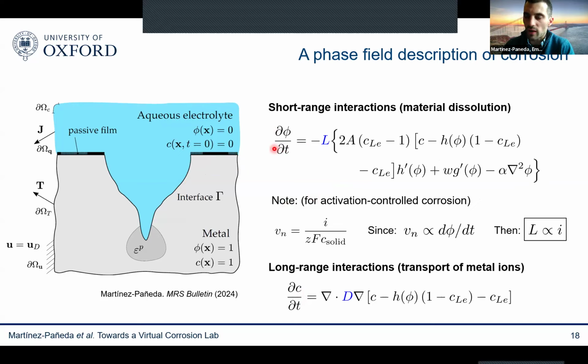An equation for the short-range interactions. So the phase field equation, which is basically simulating material dissolution, so the detachment of metal atoms. And then another equation for the long-range interaction, which is the transport of metal ions. And you can see here basically that these two equations depend mostly on these two parameters: the mobility coefficient L and the diffusion coefficient D, and both have a clear physical meaning. So D is a diffusion coefficient we can measure very easily in experiments, and L, this mobility coefficient, you can see that for the case of activation control corrosion is proportional to the corrosion current density. So you can run a very simple experiment in 1D under activation control corrosion, and then you can correlate that mobility coefficient with your corrosion current density.